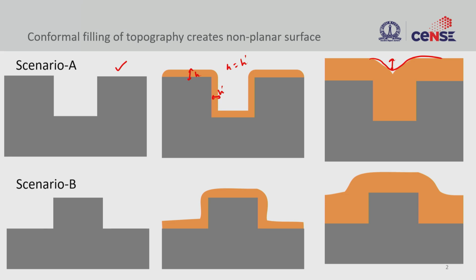This is the case of a trench. Now let us look at an isolated line, where we have space at the sides. Here again we start with a conformal deposition process, depositing the material around and then increasing the thickness. But then we end up with a sloped sidewall, and it's not going to be flat. This is a problem if we want to build circuits on top of this. Not necessarily a large number of layers; even one additional layer, the topography here could cause serious issues.